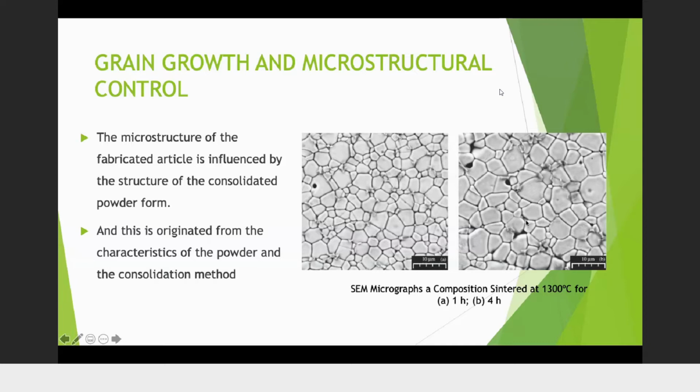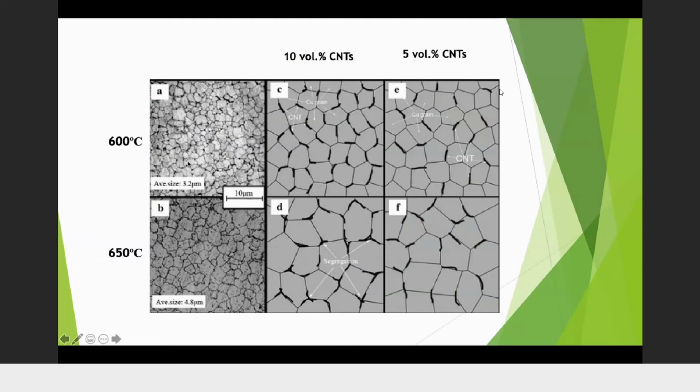So you can see that the longer you allow the sintering to happen, the more significant the grain growth becomes. And also we can see that the pores formed are bigger than you have at 1 hour.